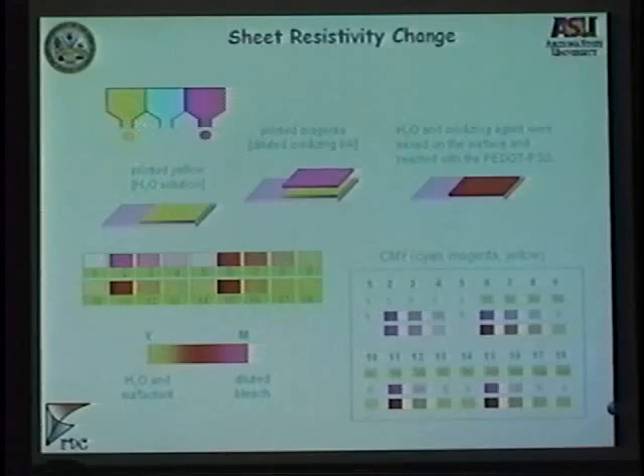That's how small these drops are coming out of the nozzle. And we allow the mixing according to a color code. We have all these color codes, as you can see here, 100% for water. And then we start changing the printing density of the sodium hypochlorite. And we can build a library according to this color code that you can get from the PowerPoint. And you could build a library of sheet resistivities.